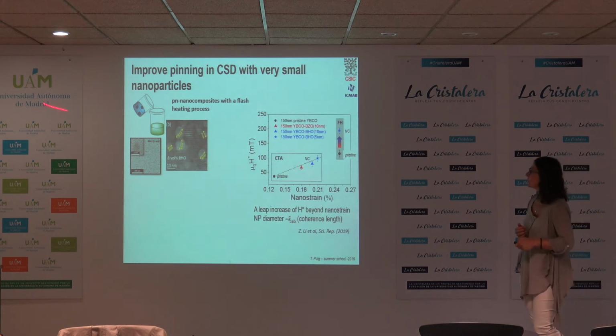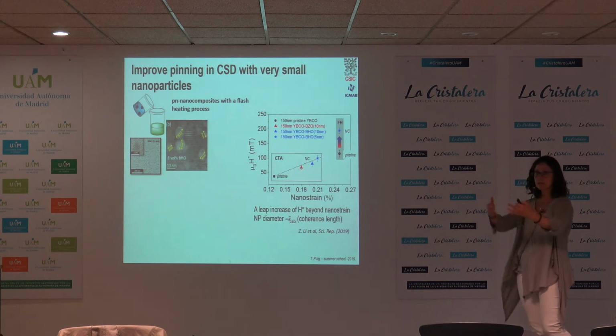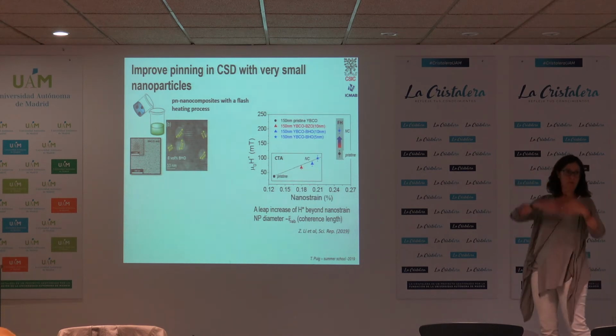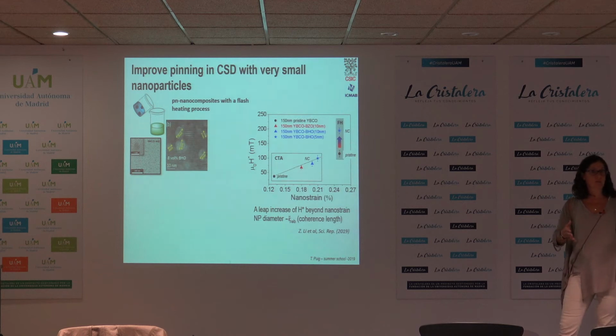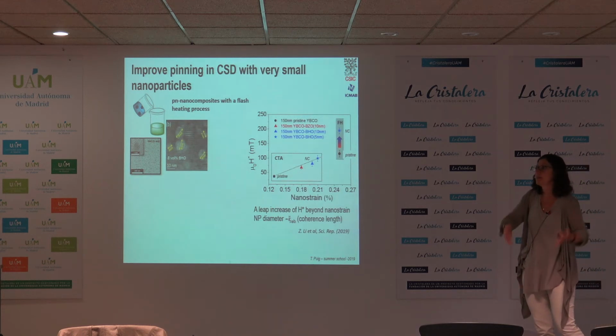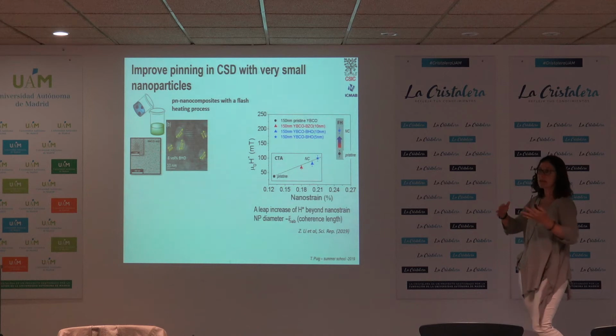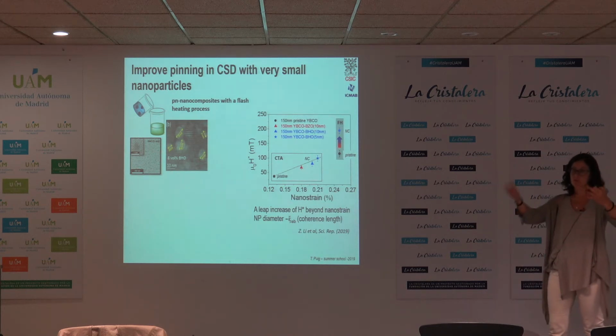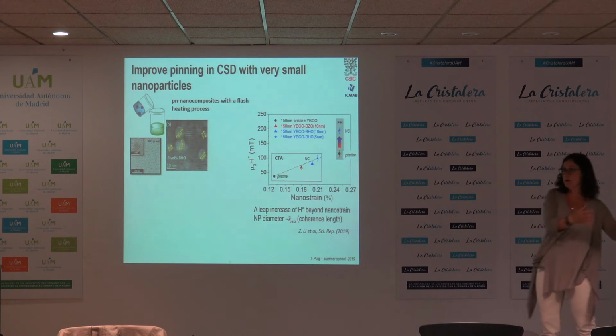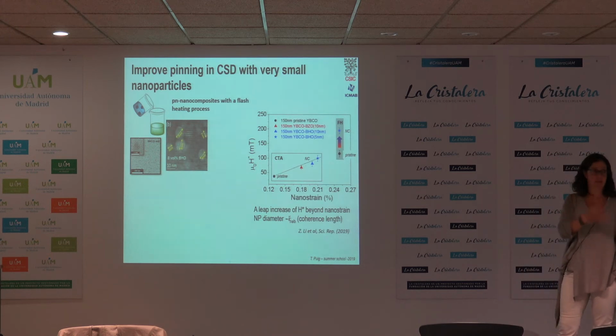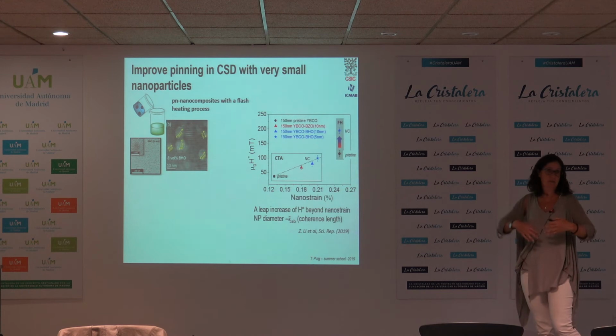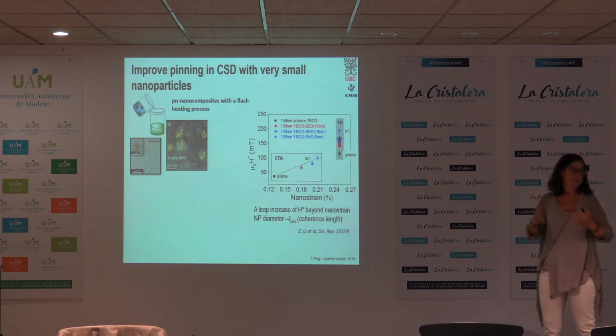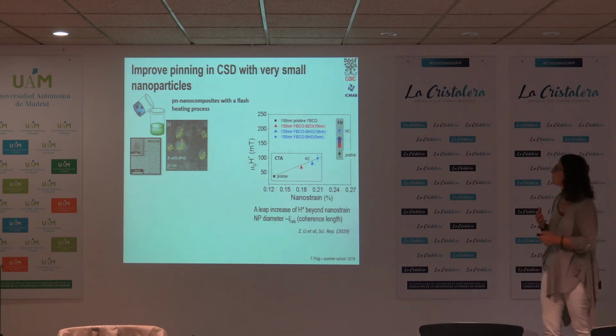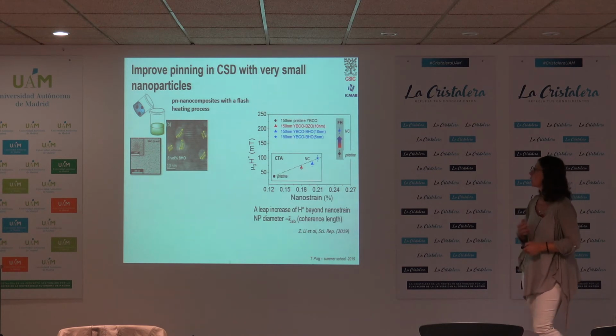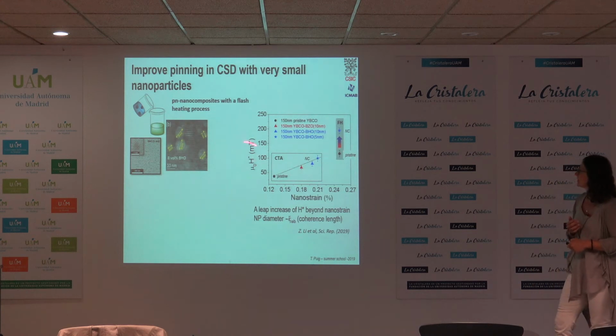And to do this, what we have done is to prepare first the nanoparticles and then throw them into the solution of the YBCO, having a colloidal solution, and then grow the material. In this case, the nanoparticles do not have to spontaneously segregate during growth, but they are already there in the phase that we want with the size that we want. Of course, then you have to avoid that these nanoparticles coarsen. And this has also taken quite a lot of effort, but doing very fast heating processes, we are able to encapsulate small nanoparticles.